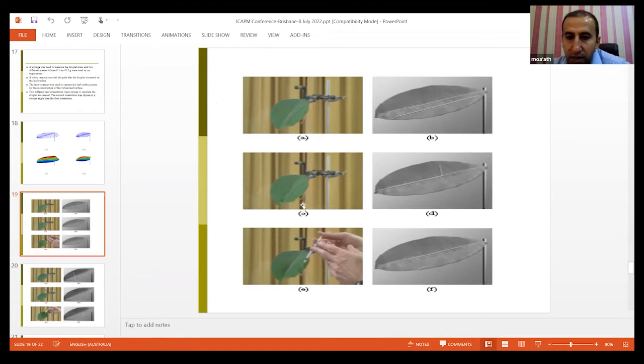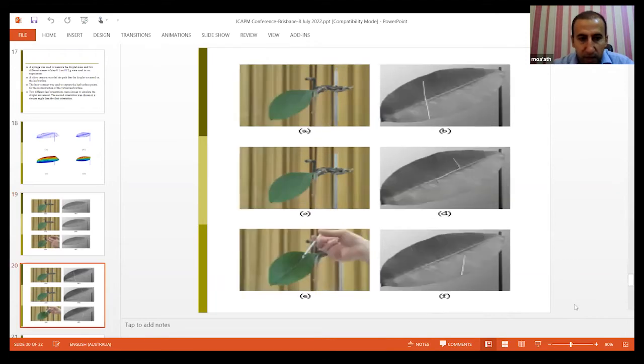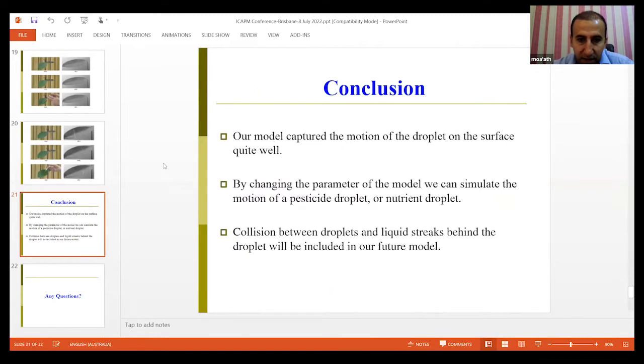As well, in figures C and D, you see the droplet start moving from the upper side to the leaf vein, then along the leaf vein, which is exactly what we obtained in our model, similar in the last figure. Here are some more experiments, and as we can see, our model captured the droplet movement exactly. So our conclusion is that our model captured the motion of the droplet on the surface quite well. By changing the model parameters, we can simulate the motion of pesticide droplets or nutrients. Collision between droplets and the liquid streak behind the droplet will be included in our future model.